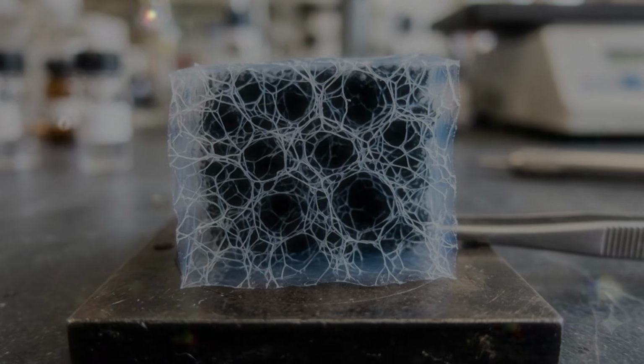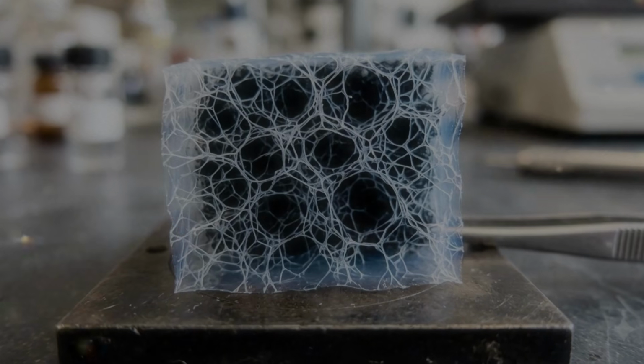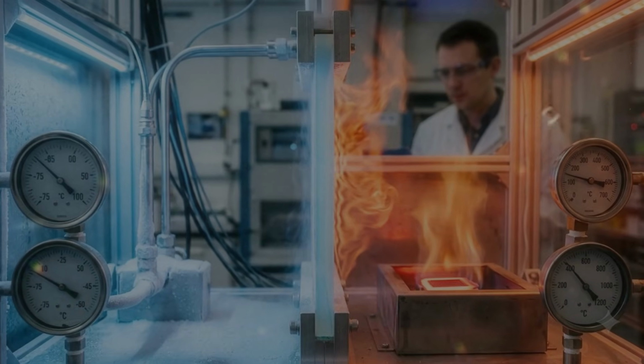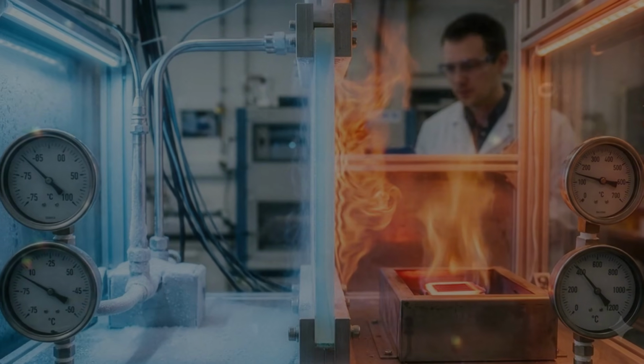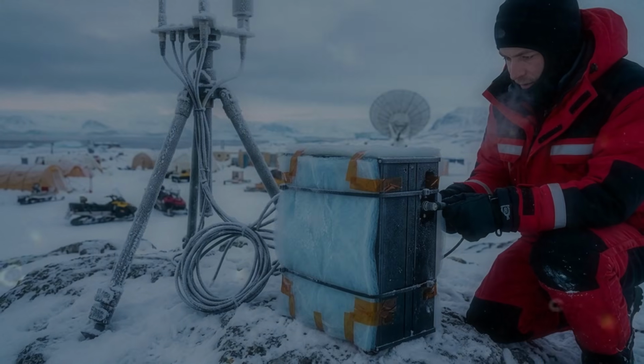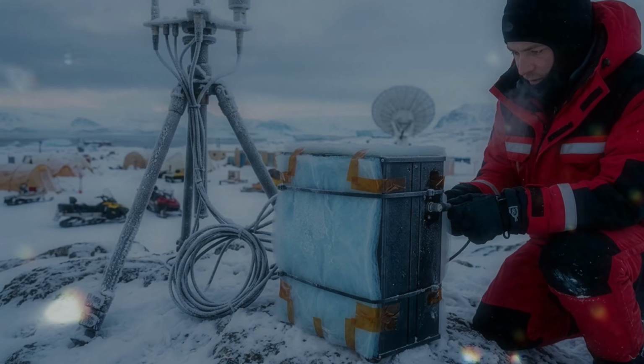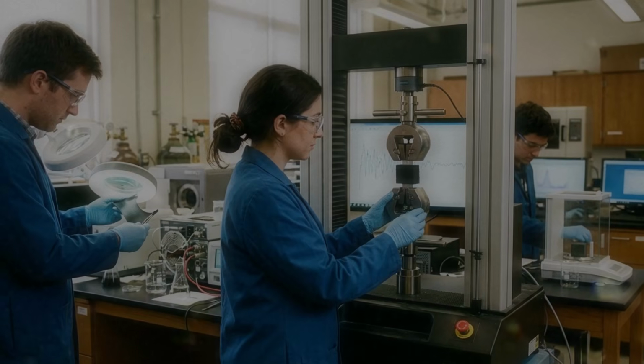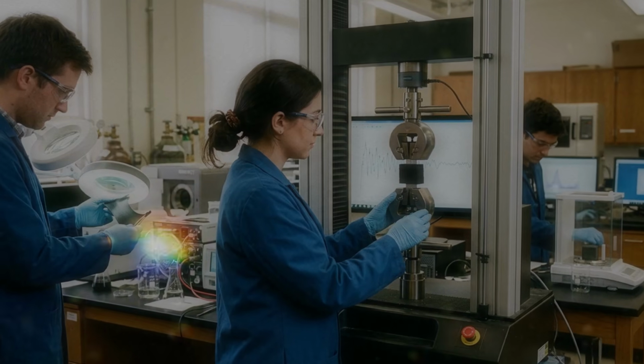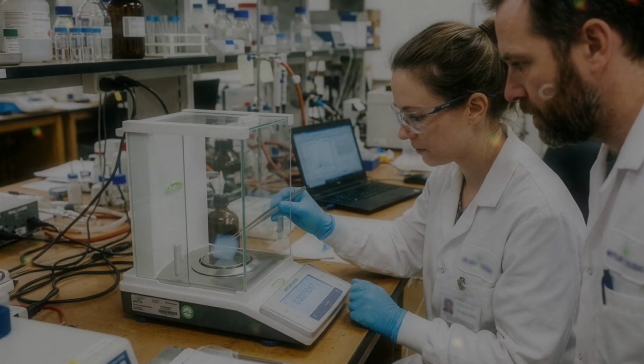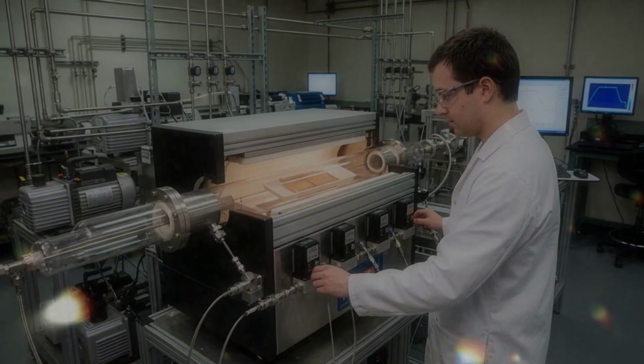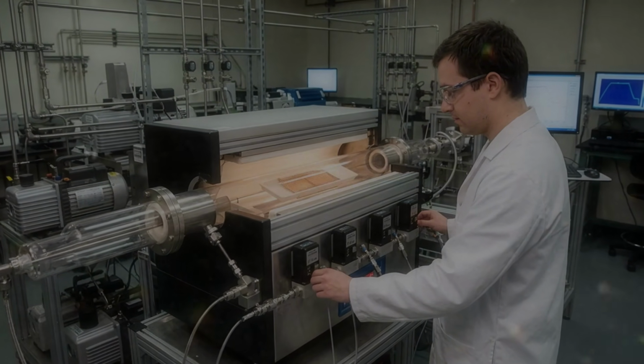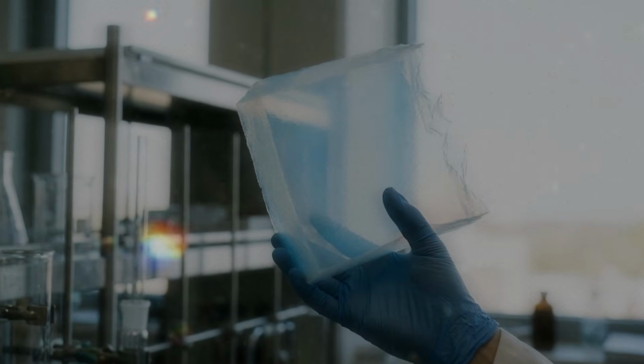Carbon aerogels can conduct because carbon provides pathways for moving charge. The level of conductivity depends on how the carbon is arranged. A dense network with many contacts usually carries current more easily than a very sparse one. Reduction and heat treatment can improve the conductivity of graphene aerogel. Graphene oxide contains oxygen groups that interrupt the carbon network. Removing many of those groups restores longer paths through which electrons can move. The removal is rarely perfect. Defects remain. Sheets meet at awkward angles. Some contacts are weak. The finished aerogel therefore does not conduct as well as a perfect graphene sheet, but it can conduct well enough for sensors, electrodes, heaters, and other devices.